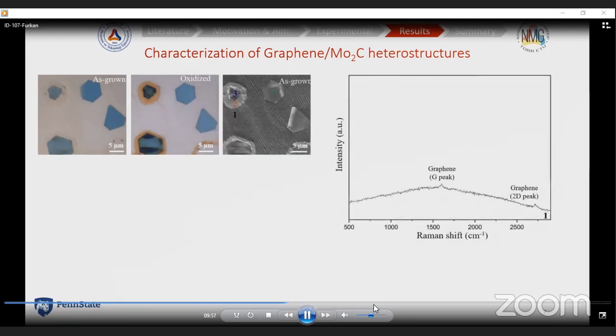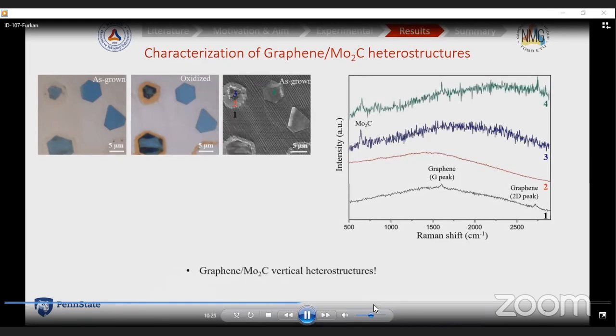So this was further confirmed by Raman spectroscopy. So this is the SEM figure of the same sample, and the Raman spectrum taken from region 1 shows only graphene features, while in region 3 there is no peak at all because it is bare copper, and in region 2 only molybdenum carbide, as expected. And at region 4, the crystal grown on graphene, we observed graphene and molybdenum carbide peaks.